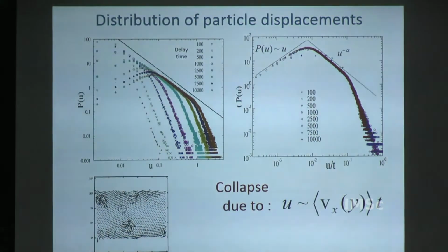So what you are getting here is somewhat in between a fluid, or rather an amorphous material, and real crystals. Crystals have these defects, whereas you cannot define defects in an amorphous material. I showed you that these hot spots are coming because of coalescence of these defects in a very particular fashion, so that is very much solid-like. You have these grains that are solid-like. On the other hand, you have this velocity field which is very much fluid-like, or at least amorphous material-like. So it's kind of a mixture of these two.